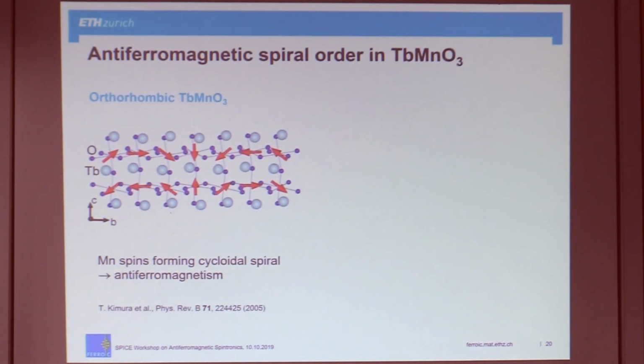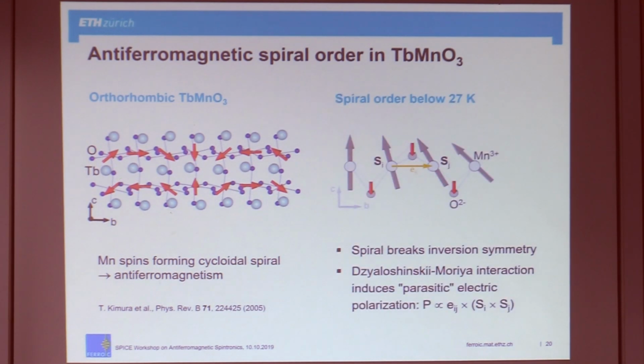So we took an antiferromagnet of this spin spiral type, terbium manganite. Here you see the spiral very nicely. And remember, because of that spiral, you have a very small, really very small secondary improper electric polarization. That is your handle to see the antiferromagnetism. But it's in a different space, kind of. It's not in spin space. So you look at the polarization, or you do something to the polarization, and it doesn't interfere with spin space so much.